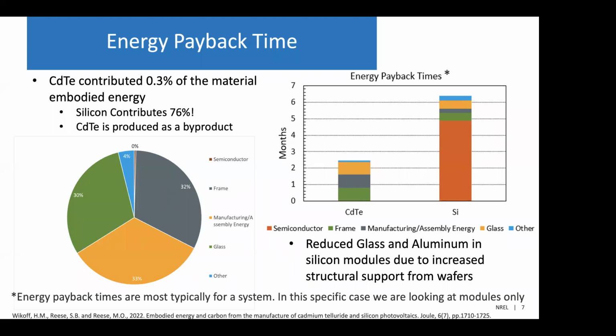But one of the reasons why this is a good proxy for perovskites is that you can see that all of these aspects that are really driving the energy for CadTel are going to be really similar for a perovskite: your glass and your aluminum frame. And we actually were trying to be pretty conservative with our energy consumption numbers. One of the reviewers actually came back and said that we were overly conservative, but we were trying to use internal models, rather than something else. And we were already coming down pretty hard on silicon.